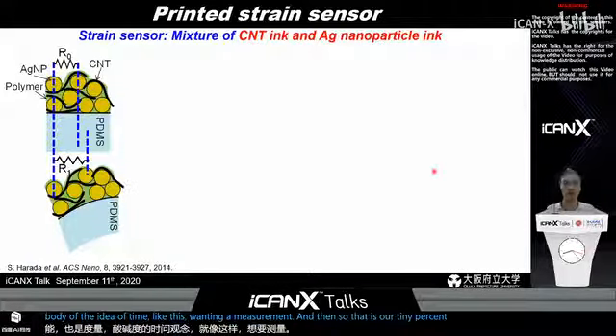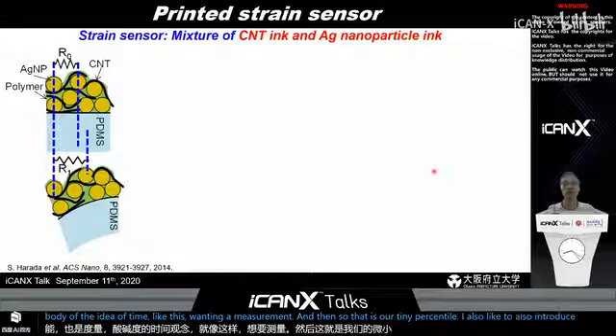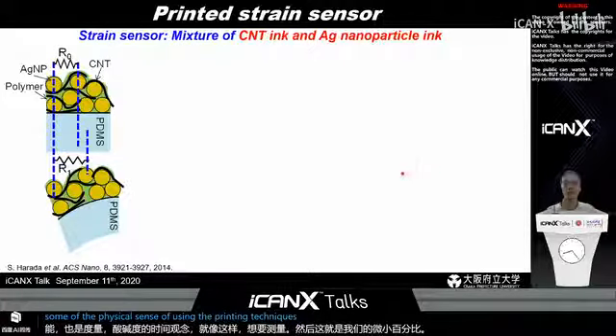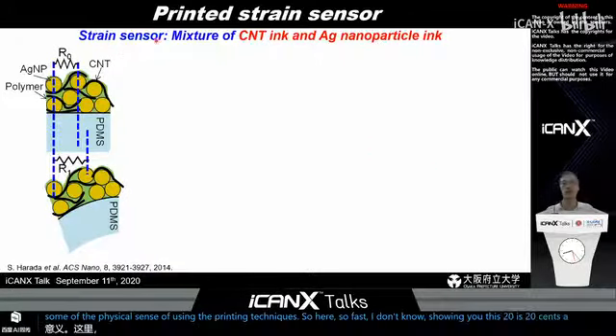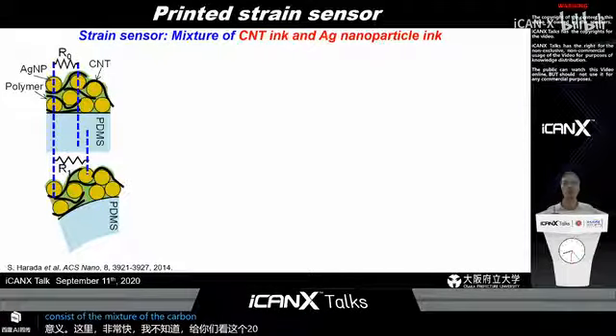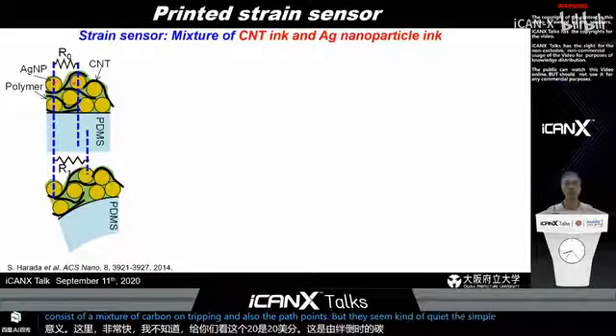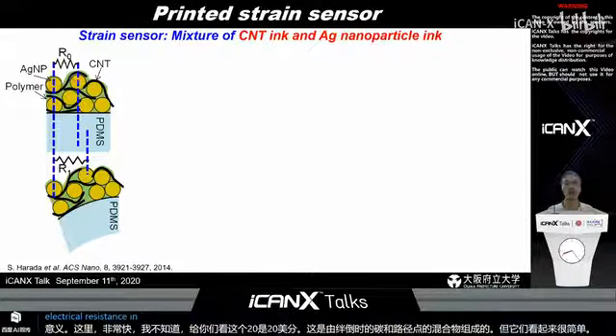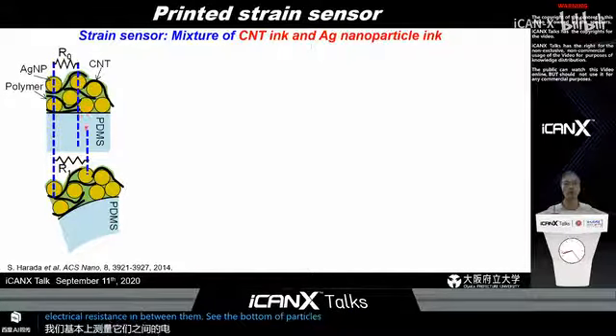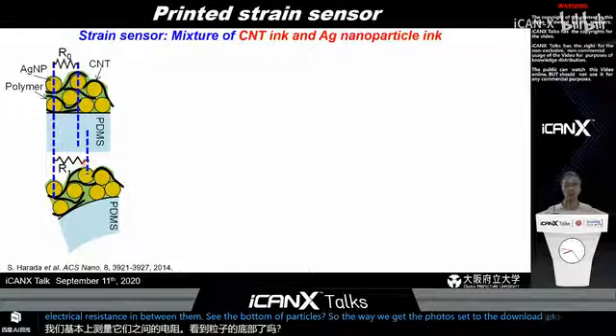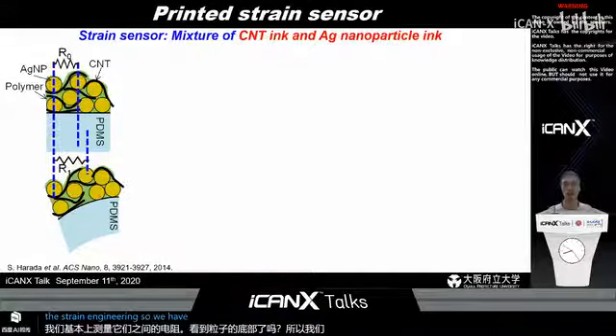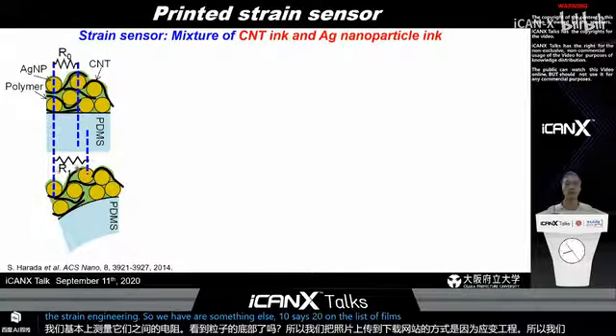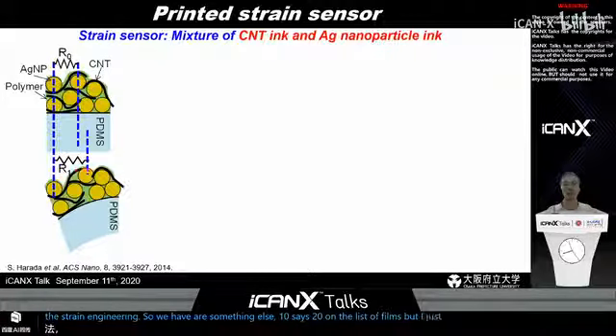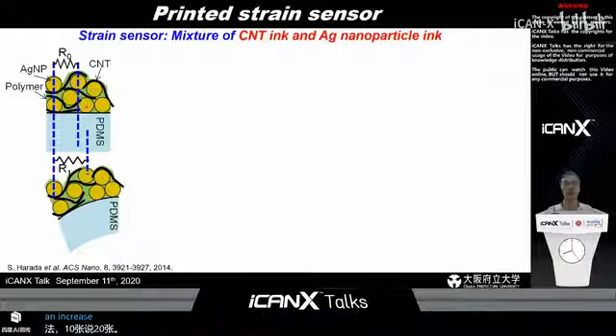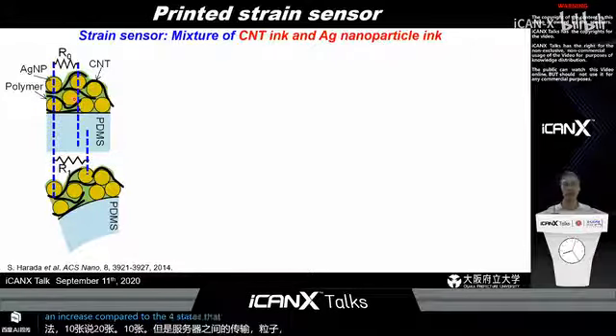I would also like to introduce some physical sensors using printing techniques. First, I want to show you the printed strain sensors. The strain sensor consists of a mixture of carbon nanotube and silver nanoparticle inks. The sensing mechanism is quite simple: we basically measure the electrical resistance between the silver nanoparticles. When we bend the substrate to the downward side, due to strain engineering we have some tensile strain on these films, so the distance between silver nanoparticles is increased compared to the flat state. That means the electrical resistance should increase.